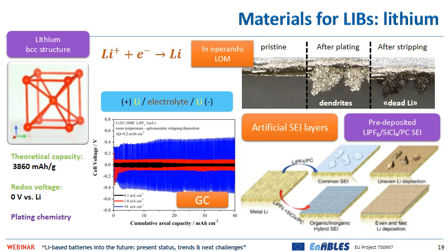In order to prevent this formation, various strategies have been proposed in the literature. The first, the most successful one, is the formation of an artificial SEI layer on the surface of lithium.